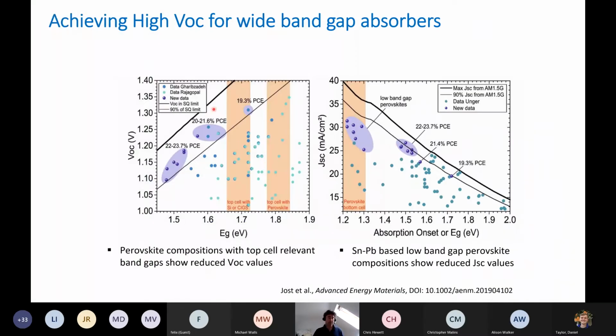So I'm showing you here a plot of open circuit voltage against band gap for a range of different solar cells from literature. And what we generally find is as you increase the band gap, there's more and more difficulty in increasing the open circuit voltage. There's a few examples where surprise results have been achieved, but generally it's hard to push the open circuit voltage up. Current density is more easy to obtain, and these lines show what you'd expect.